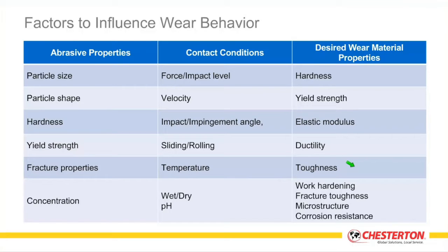Particle shape also has an impact. Here, the velocity at which that particle is impacting the surface will have an impact on the yield strength of the substrate. And then you get to some of the other ones, such as hardness, which will also have an impact on the impingement angle. And there you're looking more at the elastic modulus of the base metallurgy or the base substrate. As you look at each one of these abrasive properties and the contact conditions, the desired wear material properties are indicated in this table here. So we can use this as a way to define where properties are most beneficial to providing the performance attribute that you're looking for.